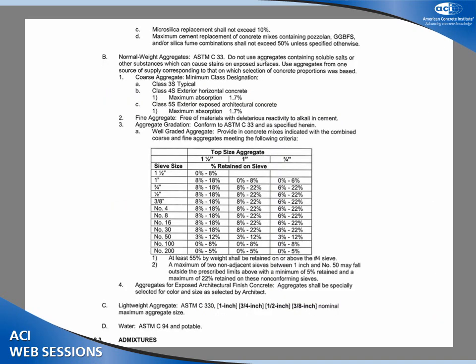I like to show this slide too because it's part of our specifications, and it's also a critical part of our mixed designs, and that is we recommend on most of our concretes a well-graded aggregate. This is important. This is the Shilstone 818. Now I'll tell you that I've never rejected a mixed design because it didn't meet the letter of 818. I'm a realist, and I know that that's difficult to do. As long as an honest attempt is made to get these larger aggregates in the mix, the whole point is reducing the water demand of the concrete and aggregate packing the concrete so you can lower the paste value.